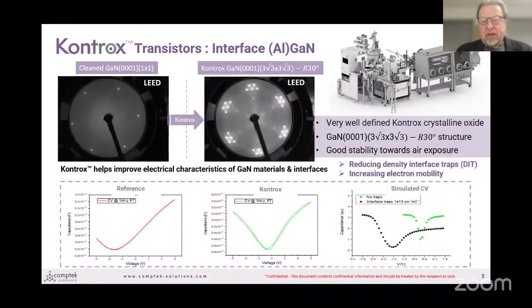Some examples of the technology effectiveness are, for example, the interface. Here we have pictures from a gallium nitride wafer that is clean, and then we have started growing our Kontrox oxide, and you can see that it's a very well-defined oxide with a very specific structure, and it has a very good stability towards air exposure that lasts for weeks, I would say. And in this example, we help to reduce the density of interface traps for the electrons and also to increase the electron mobility.